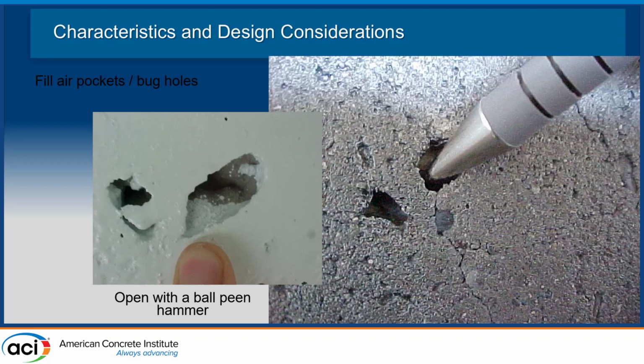So you have a void in the concrete, and you really can't coat into that bug hole. So you have a discontinuous coating film there. So we're in a very corrosive environment, and we have basically a discontinuity of the coating film. That's a coating failure point. That's where the concrete can still be attacked by the environment or the commodity that's there.